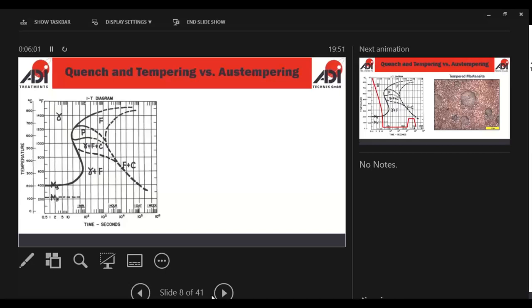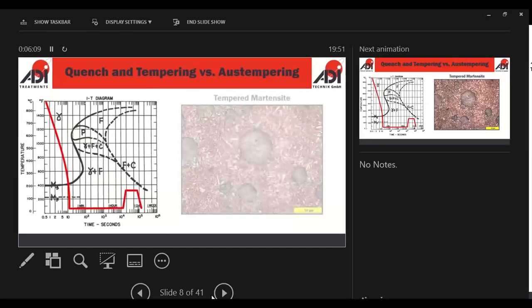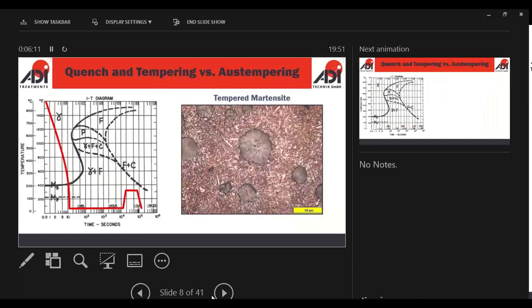These are just obviously the main hardening process you have. You can either quench and temper, the traditional way of processing irons and steel. Here you heat your castings or forgings, let's say if you're into the steel, up to say 850, 900 degrees centigrade, quench them into an oil or water. This creates a martensite, which is very, very strong, but also very brittle. So you have to temper out the brittleness.